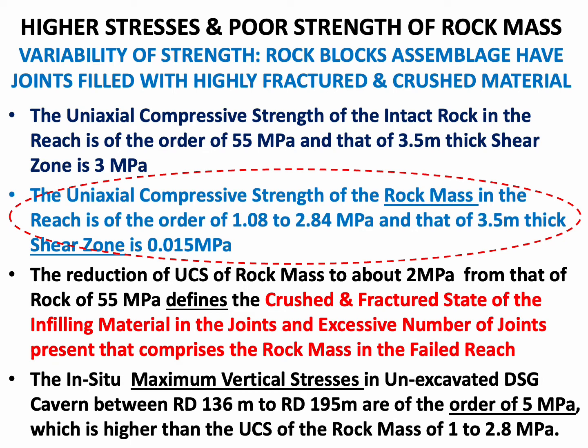So see the comparison, the variability of the strength of the intact rock and the rock mass which comprises it. The intact rock exhibits strength of 55 MPa, whereas the rock mass, which comprises these intact rock and fractured and shear zones, shear seams and clay filled joints, exhibits only a compressive strength of the order of 1.08 MPa, from 55 to 1.08 MPa. This is the variability of the strength range. Also, the 3.5 meter thick shear zone is only exhibiting uniaxial compressive strength of 0.015 MPa.